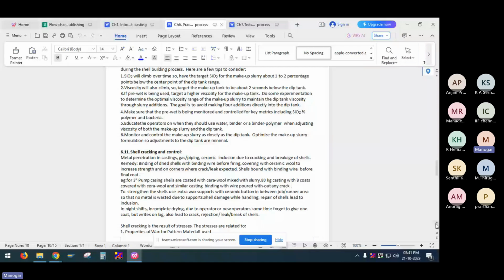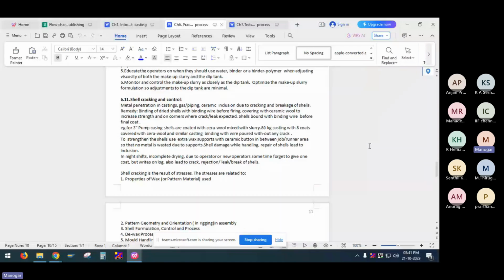And for shell cracking and control: metal penetration, casting gas piping, ceramic inclusion are due to cracking and breaking of shells. So these are the defects due to shell cracks. The remedy is binding up dried shells with binding wire before firing, covering with ceramic wool to increase the strength at corners where a crack or leak is expected. Shells are bound with binding wire before the final coat.